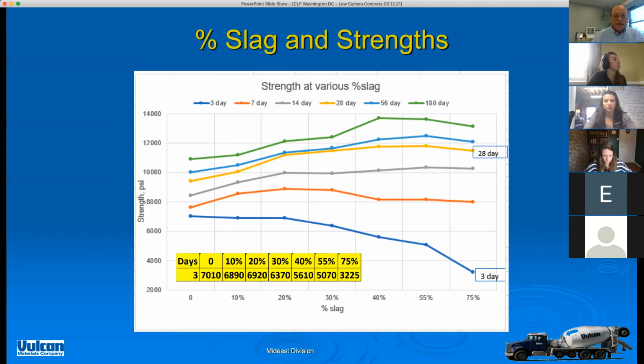There you go. Okay. And so the 3-day strength, when you have 0% slag, it's breaking at about 7,000 psi in 3 days. But as you can see, as you increase the percent of slag, the 3-day strength continues to drop, and by the time you get to a 75% slag mix, it's less than half of the 0% slag mix. So that's the impact you have on the strength development.